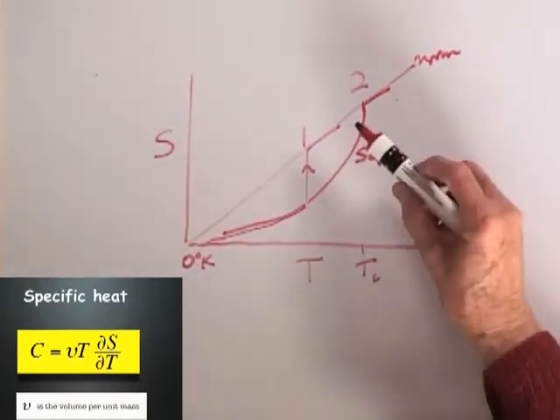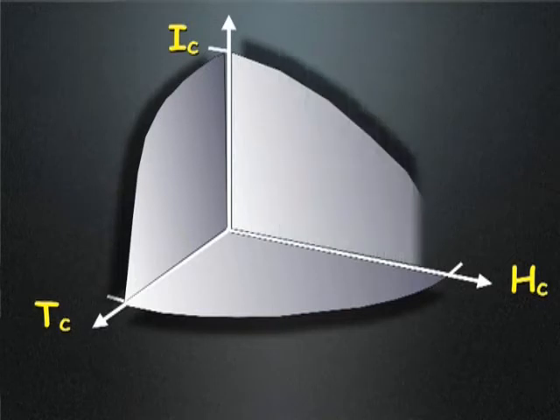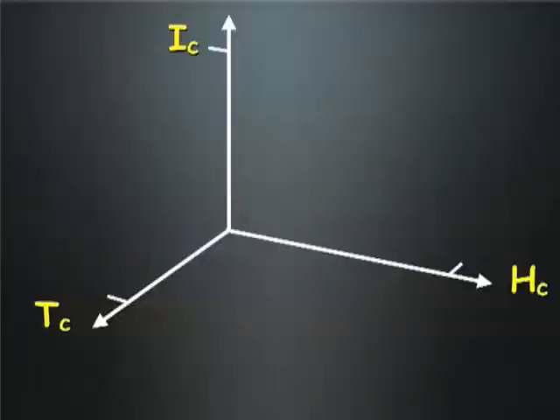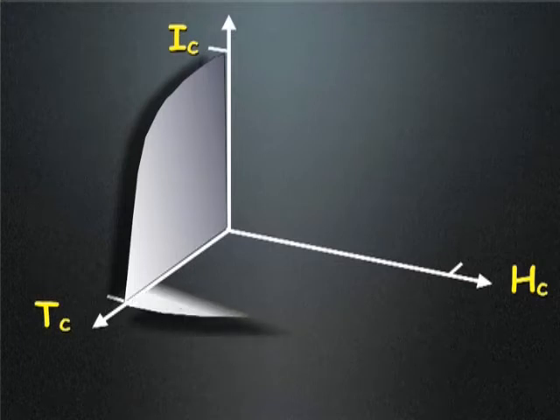The second-order transition marks not a change into something quite different — it marks the beginning of a change. One might say: let's operate without a magnetic field. Impossible — because we need superconductivity to transfer currents, and currents produce a magnetic field. So the very phenomenon for which we need superconductivity kills superconductivity. Onnes himself failed to make this connection. It was left to Silsbee to point out that the critical current was simply that current which generated the critical field at the surface of the conductor.